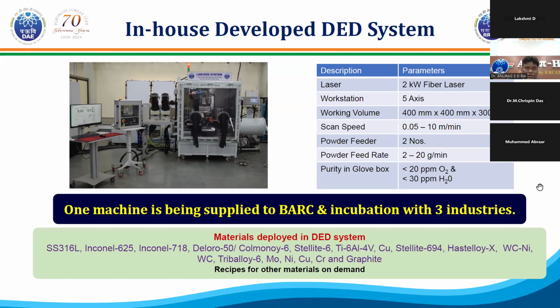Recently, we received one more requirement from our sister concern, where they want graphite deposited on some nickel-based alloy, and the thickness of graphite they wanted is in the range of 200 to 250 micron. Depositing graphite using any other means on a metal surface is really tricky. So we have some limited success in this, and we are trying to make it, and specifically these things will be used for highly corrosive environments. So something better will come out very soon out of this.